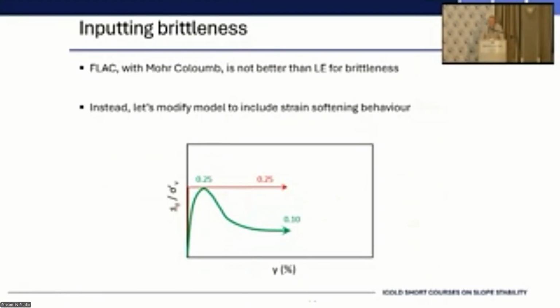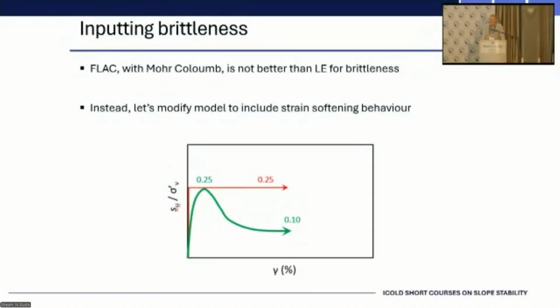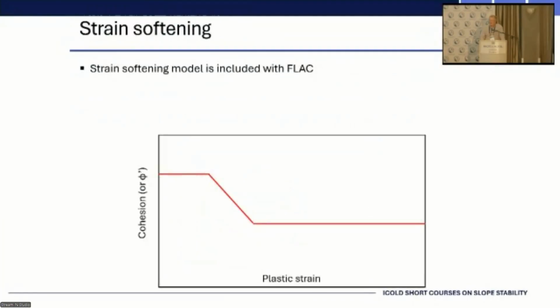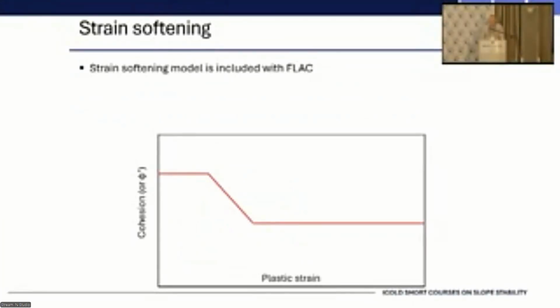So thinking about brittleness and how we accommodate that, FLAC using Mohr-Coulomb is not really that much better than limit equilibrium when dealing with brittleness. But what David did here is play with the model to include some strain softening, but in a pretty simple manner. Now, within FLAC and using Mohr-Coulomb, so not NorSand, you have this ability to do some sort of pseudo strain softening. You can decrease the cohesion, you can decrease the friction angle with some measure of plastic strain.